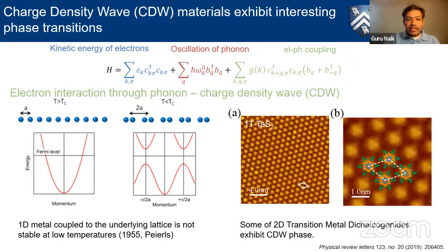Right. So this was predicted, and then of course it was observed in many materials since then. Tantalum disulfide is one of the candidates that we will focus on, which also shows this kind of charge density wave behavior. This is a 2D material, which means the charge density waves are 2D sheets of these charges. And the lattice reorganization was studied quite elaborately in the 1960s, and then recently again.